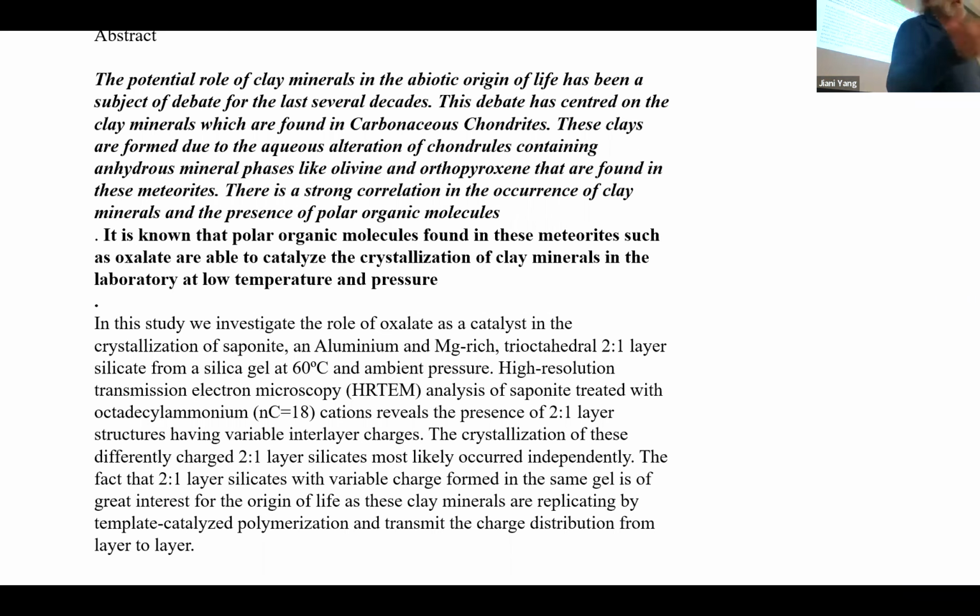We did another one just with the alkaline, no oxalic acid, and ran it for 3 months at 60 degrees in a tube that kept rotating. The result is that the oxalic acid catalyzed the clay formation way beyond the just alkaline instances.